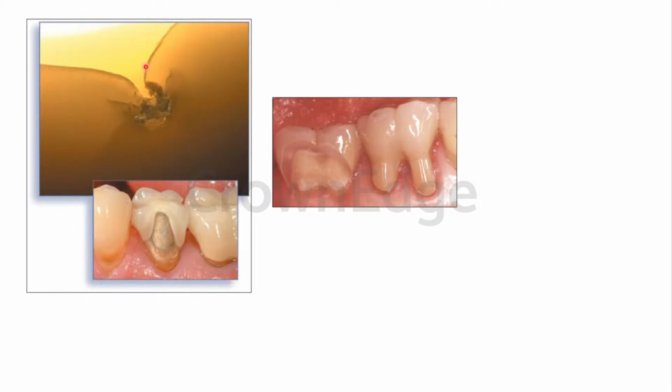This is very common with respect to your all porcelain crowns. What happens here is that a small crack is generated and that crack propagates through the ceramic material. So what we have to understand with regards to an all porcelain is that all three factors could play a major role. The first being the thickness of the porcelain, the second being under preparation, and the third being it is not rounded at the finish lines or at the line angles.